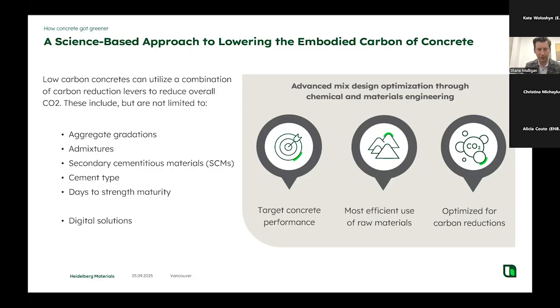And a lot of work is going on at the CSA level to increase the amount of limestone that's allowable in a PLC mix and maybe limit the applications that can go into. Another really powerful lever for us is the days to strength maturity. So, concrete is typically measured at 30 MPa in a 28-day strength time horizon. If we're able to extend that out to a 56-day horizon or 91-day horizon, that is a very significant lever